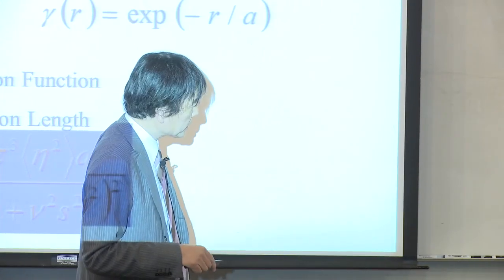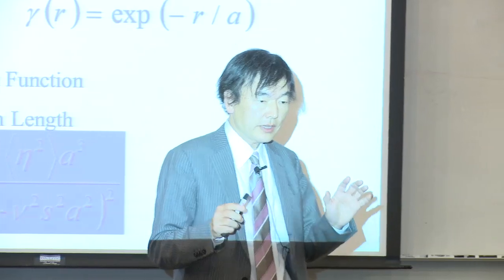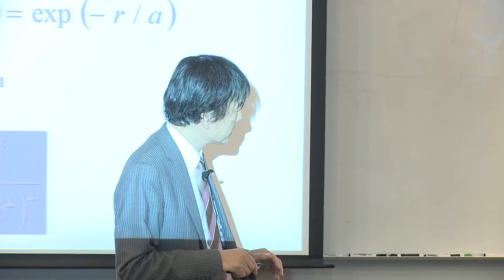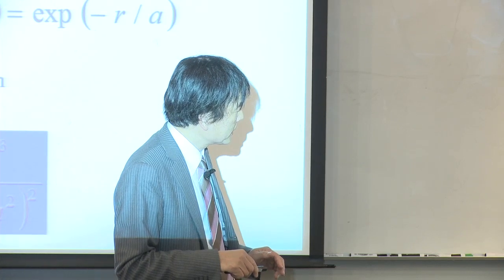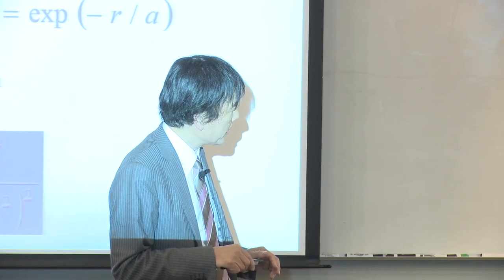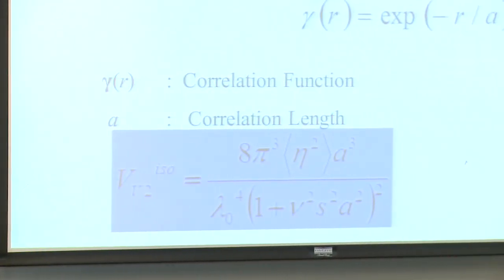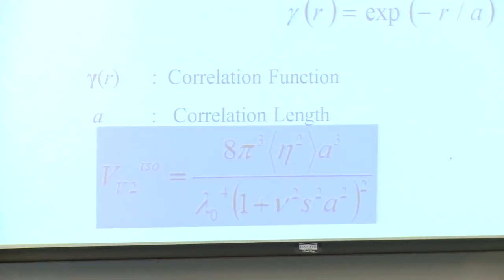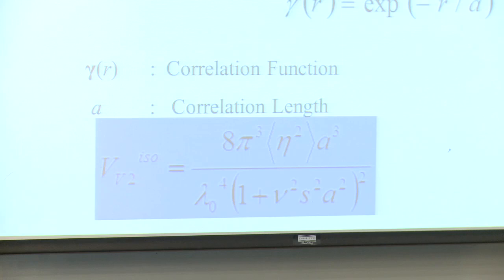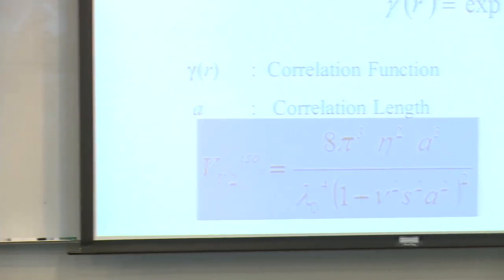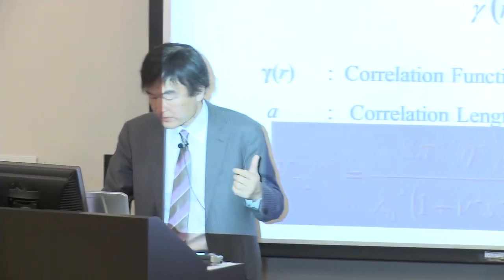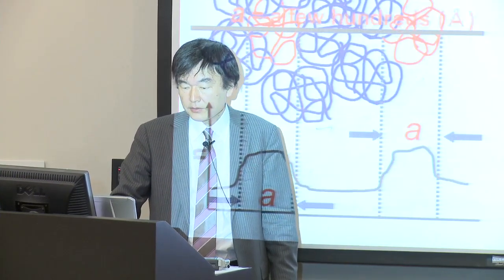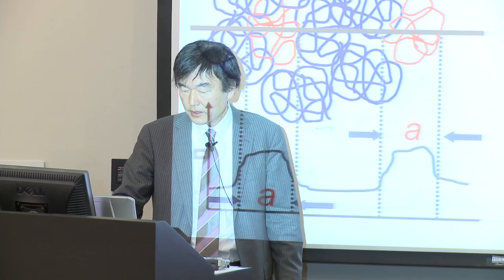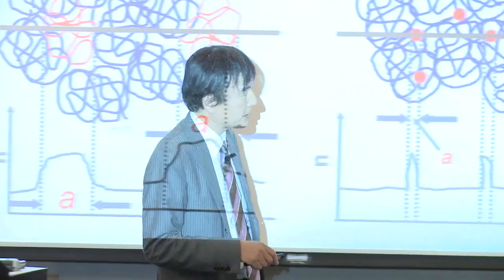With this equation, I can correlate the scattering loss with the size of the heterogeneities and the refractive index differences. The order of the fluctuation of the refractive index is of the order of 10 to the minus 5th or 6th power. It's almost overlooked, but that is causing the scattering loss.